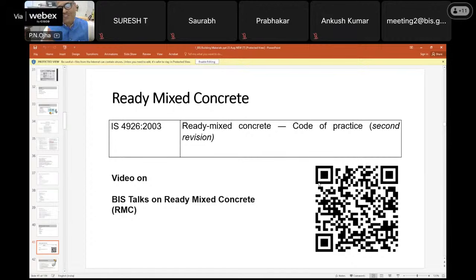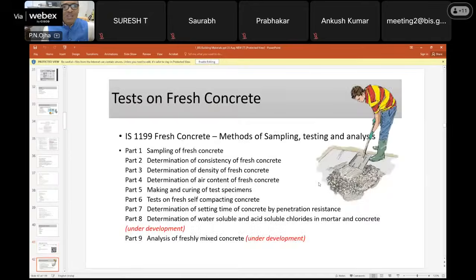As I said, standards are of almost three types: specification, test method, and code of practice or guidelines. Okay. So right now, fresh concrete: how to test fresh concrete for various properties, because fresh concrete properties are very, very important. So sampling, then consistency of fresh concrete, density of fresh concrete, air content, then making and curing of test specimens, then self-compacting concrete fresh properties, as I said, passing ability, segregation resistance, all those properties we have in part 6. Then part 7, setting time of concrete by penetration resistance. In part 8, water soluble and acid soluble chloride. This standard is under development.